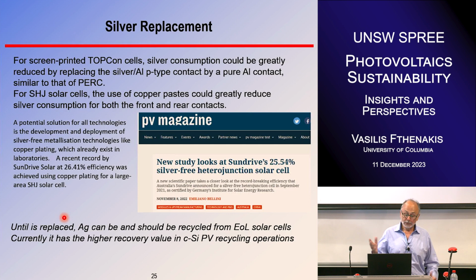But until it's replaced, silver can and should be recycled. Because with the current vintage of crystalline silicon, the silver recovery gives the highest revenue. So if you don't have silver, then you have a catch-22 situation. If you don't have silver, then recycling becomes more problematic because you don't have the value from silver.